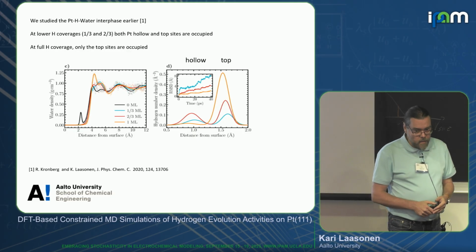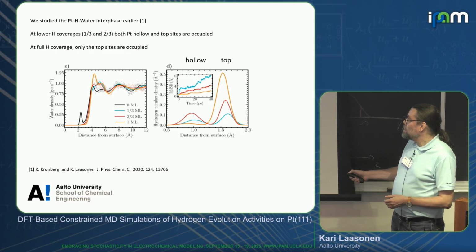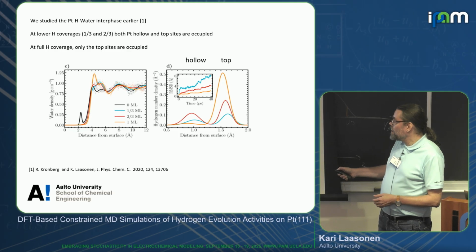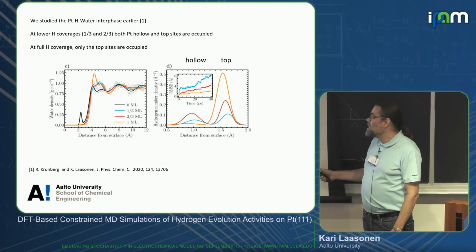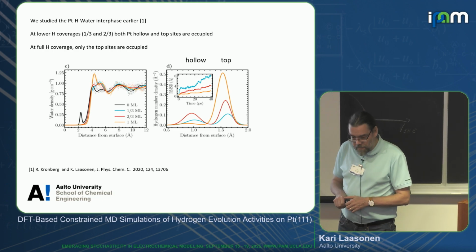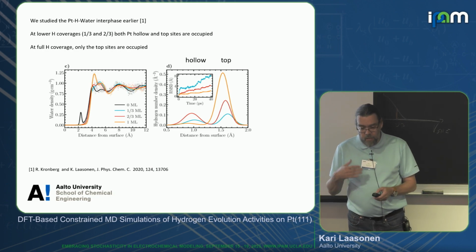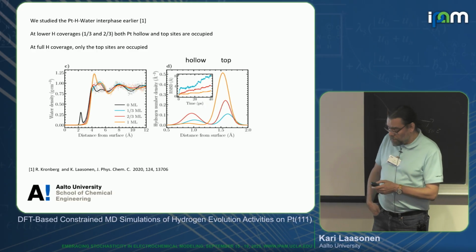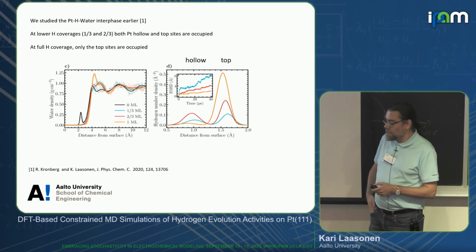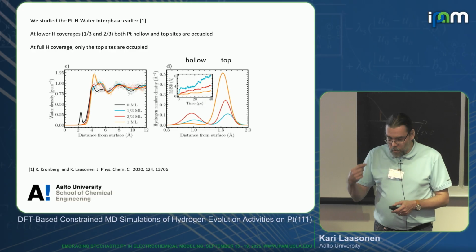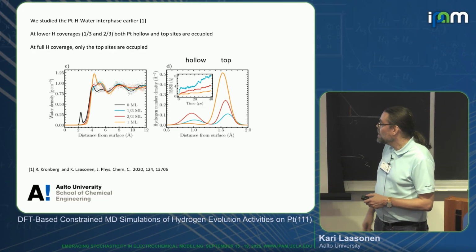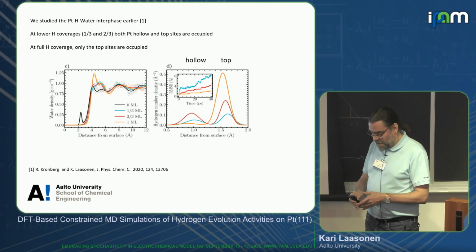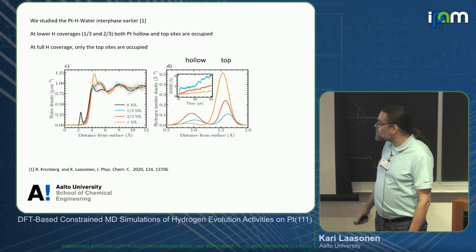And they are also relatively mobile, especially at these smaller coverages, but even here they move quite a bit. Even on this relatively short time scale of ab initio MD, they move. There are some exchange processes at full coverage, and at the lower coverage they can go from hollow site to top site and back. So there's definitely dynamics.